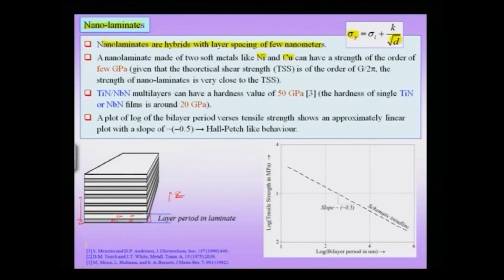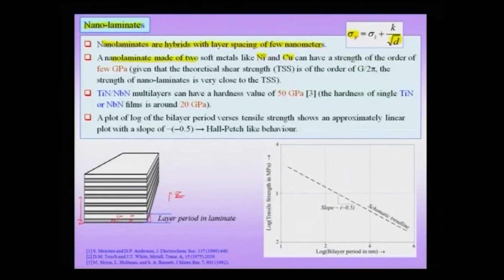Now, in the case of nickel and copper, if I make a nano laminate, that means the periodicity is of the order of 10s or 20 or 30 nanometers, then it is found that the nano laminate formed from two soft metals like nickel and copper, both FCC, that implies that the Peierls stress in these structures is small and they easily plastically deform, can have a strength of the order of a few GPa. That means we are approaching the theoretical shear strength, which is of the order of G by 2 pi, in nano laminates.